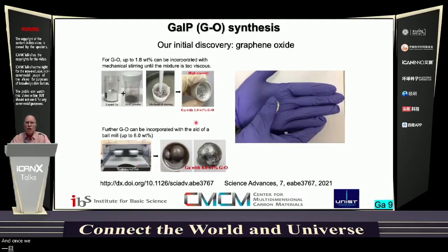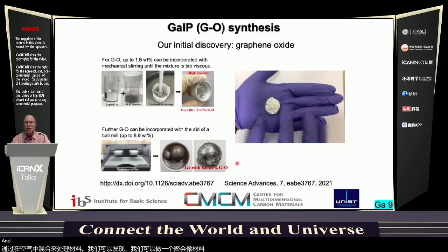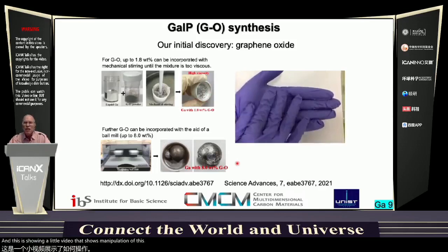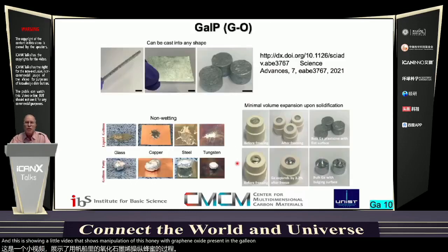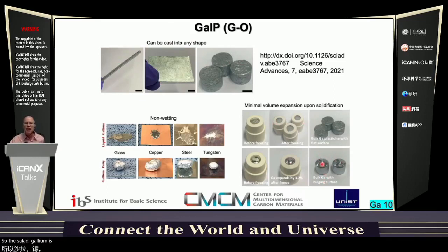And once we worked with the material by mixing in air, we could find that we could make a putty-like material. And this is showing a little video that shows manipulation of this putty with graphene oxide present in the gallium. So there's some benefits to this. It's possible to shape these composites into virtually any shape. Another fascinating thing about gallium is something like water. So the solid gallium is actually higher volume, lower density than the liquid. And as a result, when gallium solidifies, which of course, if it's supercooled, could happen near room temperature, the expansion can cause problems in certain applications. But we did learn that our putties actually don't have any volume expansion upon solidification. So we say minimal, we can say pretty much zero.